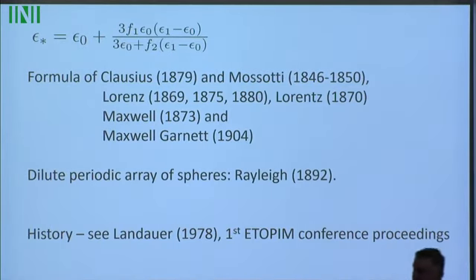There's a formula associated with this. It gives the effective dielectric constant of the mixture as a function of the dielectric constant of the air or vacuum and the dielectric constant epsilon 1 of the metal. Here F1 and F2 are the volume fractions of the two materials; F2 is actually 1 minus F1. This formula has a long history too. Maxwell Garnett is listed because he's associated with this formula in the optical regime, where these constants are complex. You notice there's a denominator here, which suggests it could be close to zero, in which case you get a resonance, and that's really what's behind the colors of these glasses.